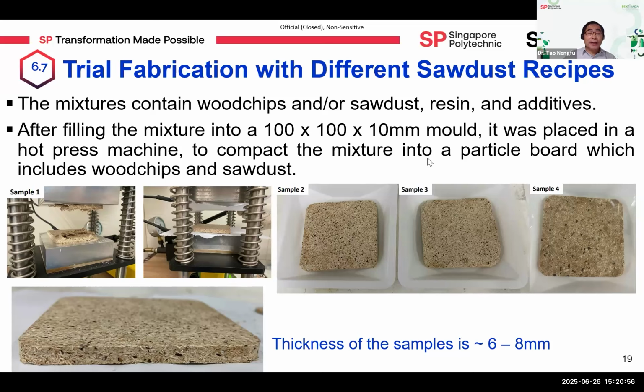Here, we fabricated the particle boards using a hot press and various sawdust recipes, achieving uniform thickness and homogeneous particle boards. You can see from the photo here these are samples of particle boards with different recipes. The thickness is from 6 to 8 millimeters.